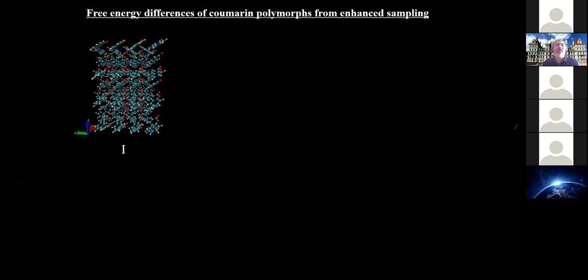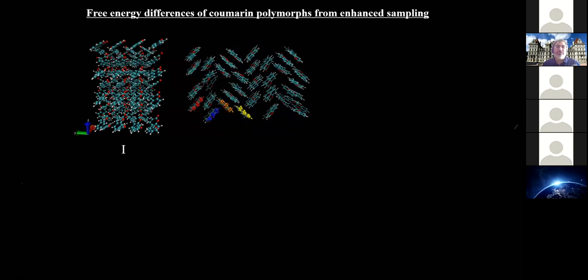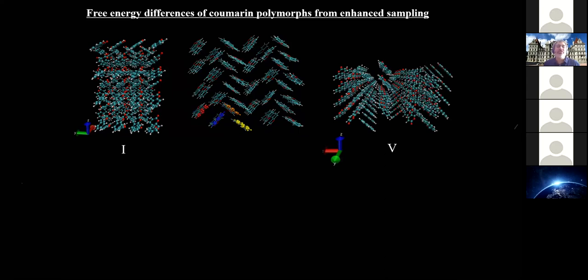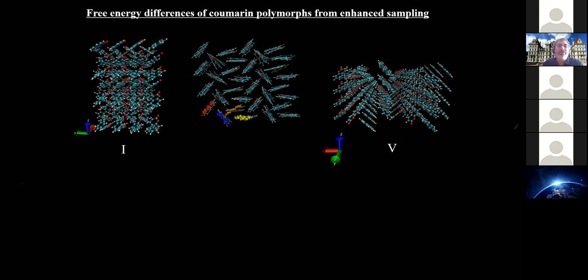Okay, so let's do this now for this Coumarin case, where we said the harmonic approximation was breaking down. Here's a typical trajectory using some of these collective variables where I'm able to generate a nice transition between the Coumarin 1 and the Coumarin 5 polymorphs. So I get a trajectory that I can then use to generate the free energy difference.